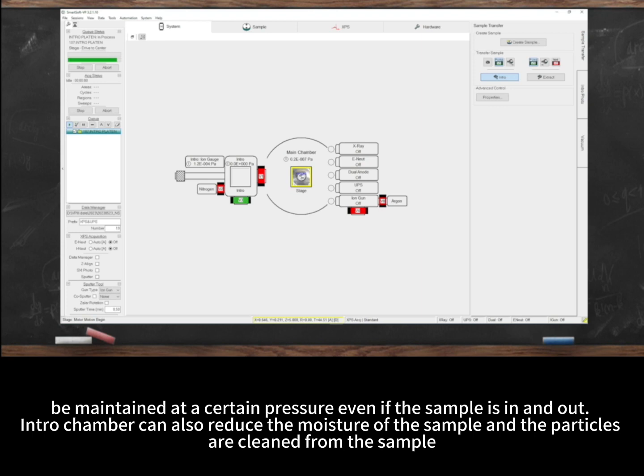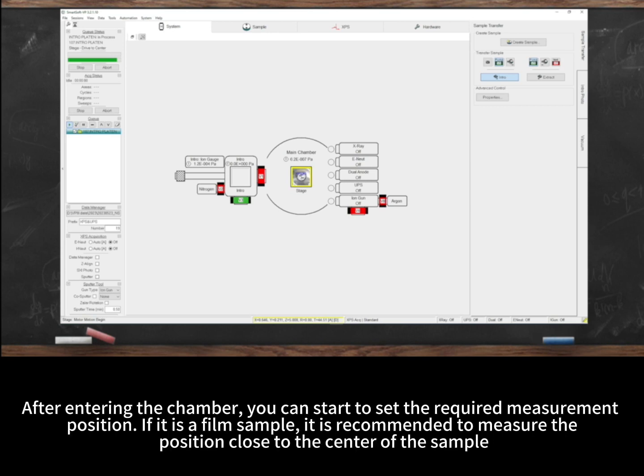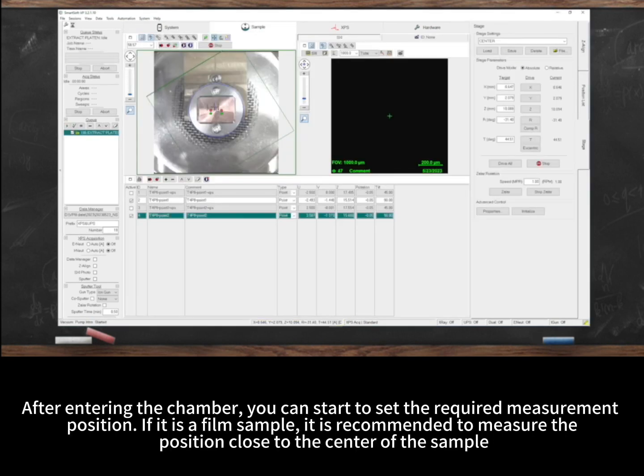The intro chamber can also reduce the moisture of the sample, and particles are cleaned from the sample. After entering the chamber, you can start to set the required measurement position. If it is a film sample, it is recommended to measure the position close to the center of the sample.